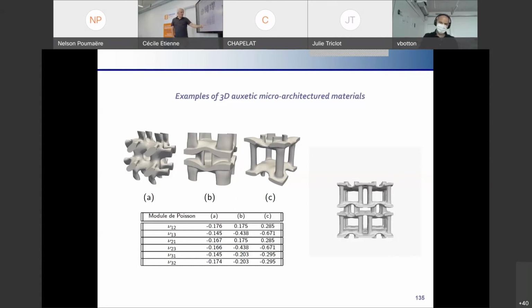It is an anisotropic material in the Hooke tensor. In B, you have three specific Poisson ratios negative, and the same for C, but not the same values. All the values are between -1 and 0.5, and the algorithm builds a new material which is auxetic, and it depends on the, I don't know the word, auxeticity. However, there are different kinds of auxetic materials, and then you obtain different kinds of microstructures.